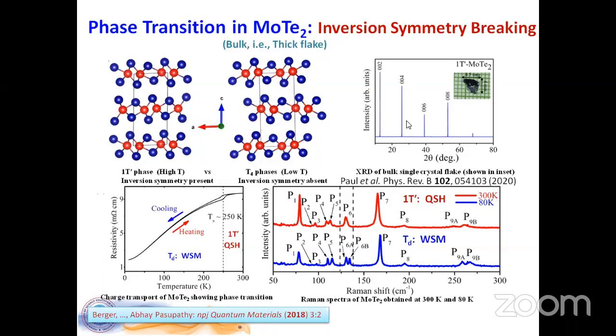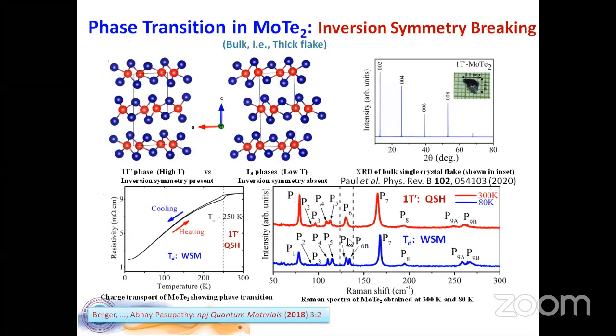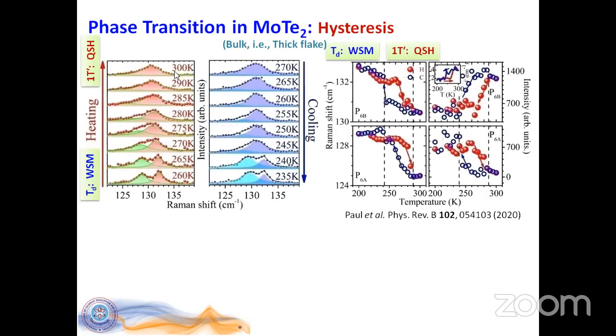Now, we just saw that there is a hysteresis in transport. So what about in Raman? So we probed this, and we could look at one of these modes. I just mentioned that this P6 splits into two modes at low temperature. So that's what we specifically followed, and we could see that at high temperature this has a single component, and as we go to the low temperature, this very nicely splits into two. And not only that, as we raise the temperature from lowest to the highest, we see that this mode again disappears. And interestingly, we see that the appearance and the disappearance temperature of this mode is not the same in the heating and cooling cycle, and that's what is related to the hysteresis discussed in the transport data.